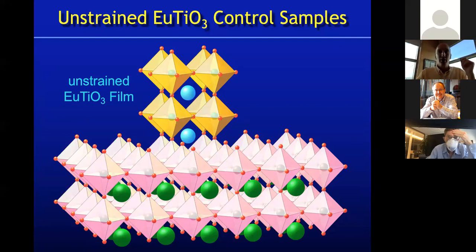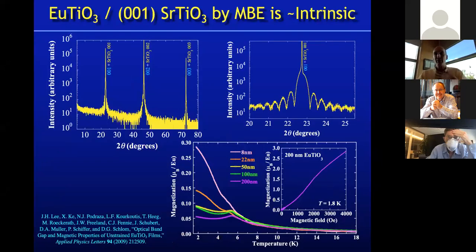So in doing the control experiment, what we saw was, first structurally, that the substrate peak and the film peak, where you see the thickness fringes here, are on top of each other. So this is when you zoom in. You don't see them on top of each other zoomed out, and you see they're on top of each other zoomed in. Also, when we look at the properties, we see that it's antiferromagnetic.